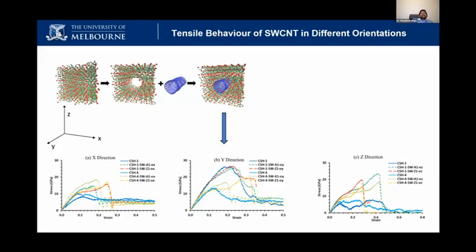Then we found the properties in different directions with different orientations. So then we can find the behavior, actually the interaction between the carbon tube and the CSH gel. What we found is that the carbon tube, even though it's strong, doesn't grip really well with the CSH. That's a weakness, because it doesn't bond properly.